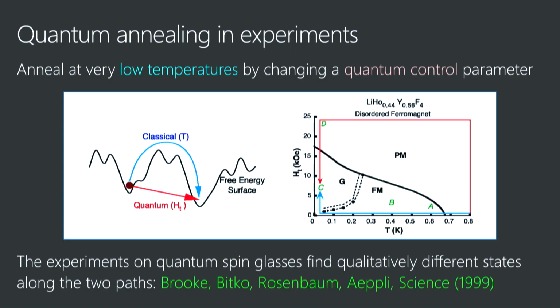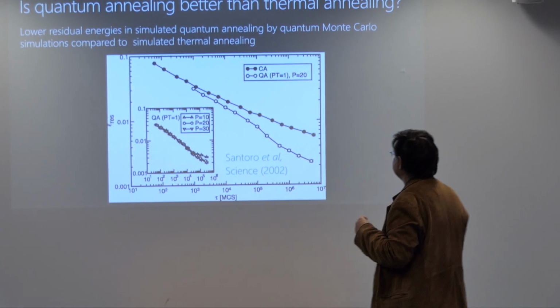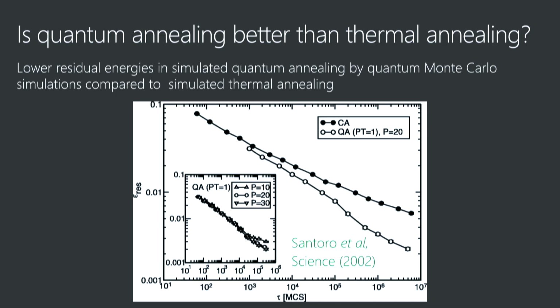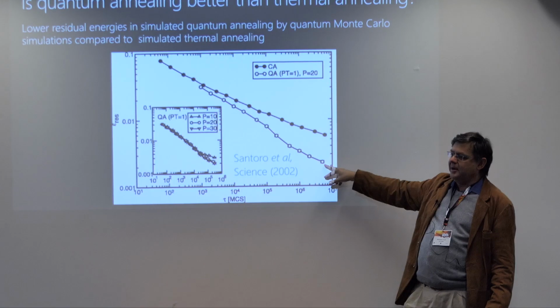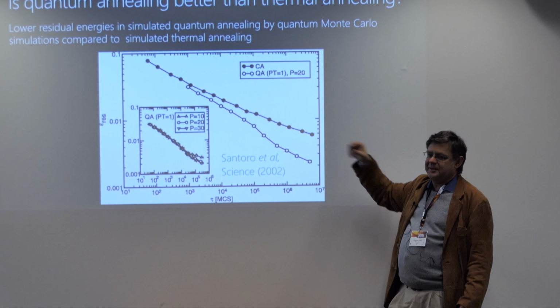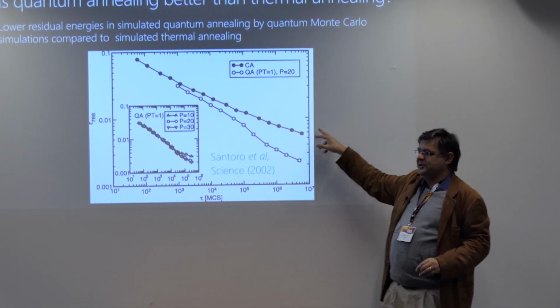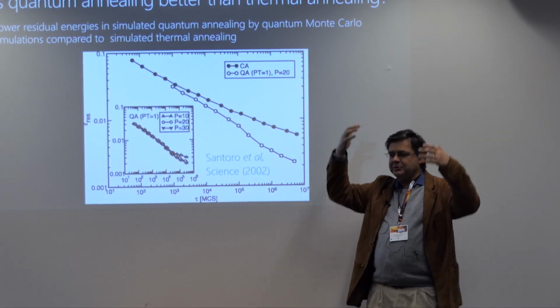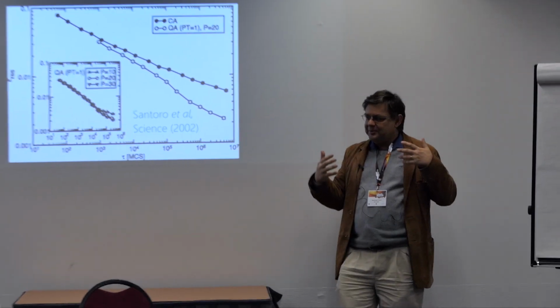So that was done here. They applied the transverse field, a strong one, cooled down in the field, and then switched off the transverse field, and they found a state that looked better. There was also a paper in Science where people simulated that and found that as a function of annealing time, the quantum annealer reaches lower energies than the classical annealer. So just the thermal cooling was less efficient than the quantum annealing, where I don't just cool in temperature, but where I start with a strong transverse field and slowly turn that off. So where the quantum effects seem to get me the better state than just the thermal cooling.